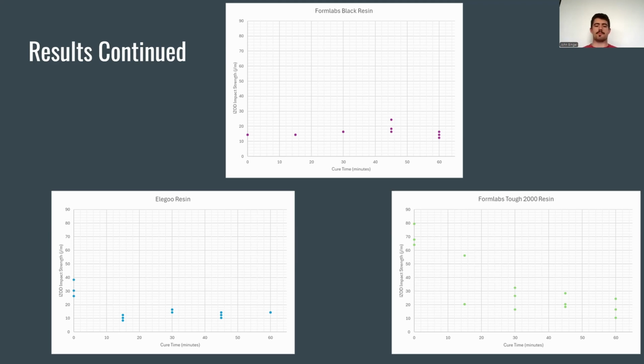The average IZOD for Formlabs Black with no cure was 14.4 joules per meter, and the same for the 60-minute cure time.